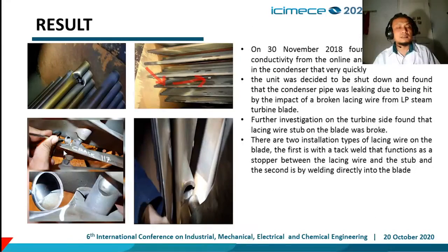This is the history of failure. On 30 November 2018, an increase in conductivity was found from the online analysis measurement in the condenser, very quickly. The unit was decided to be shut down and it was found that the condenser pipe was leaked due to being hit by the impact of broken lacing wire from low pressure steam turbine blade. Further investigation on the turbine side found that the lacing wire stub at the blade was broken.